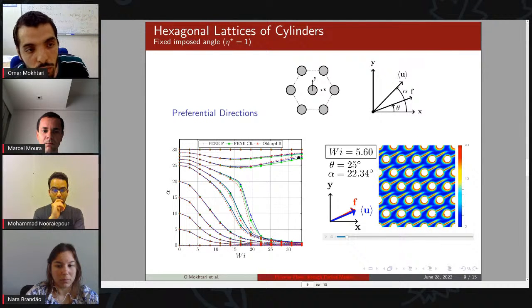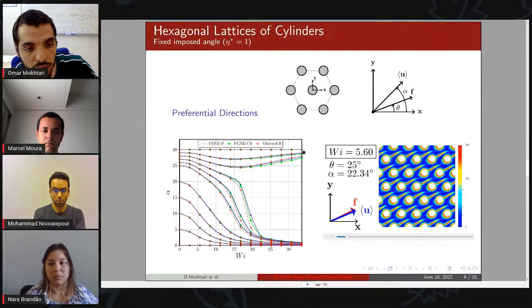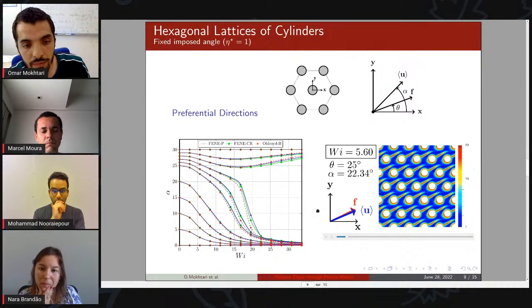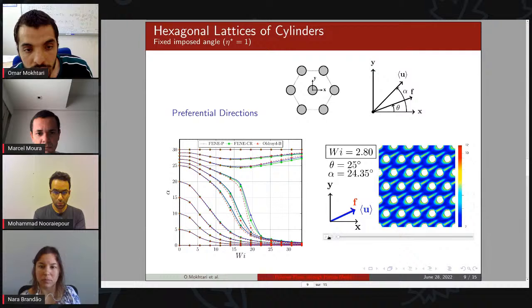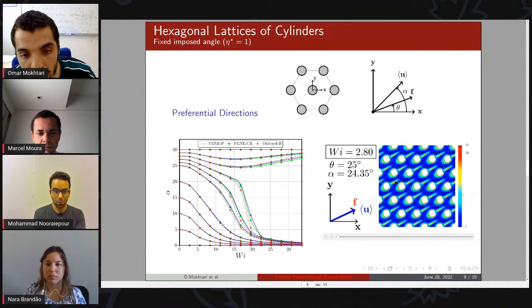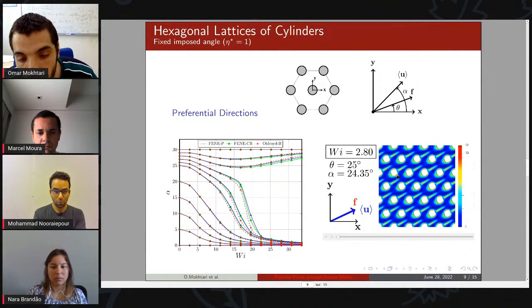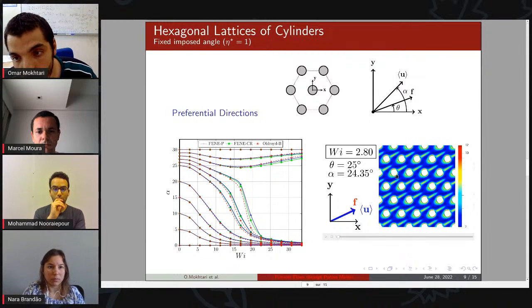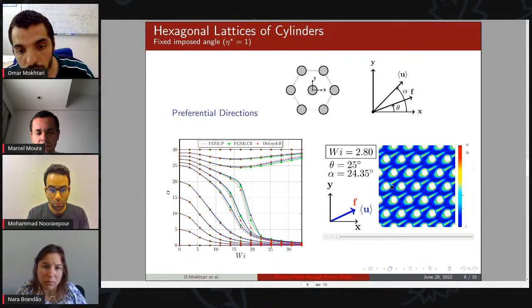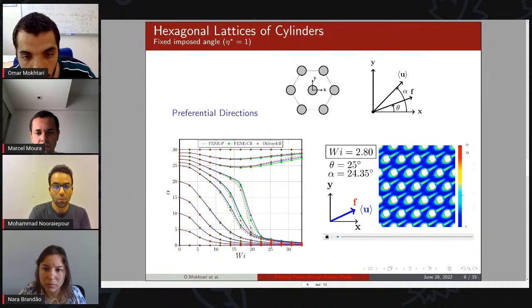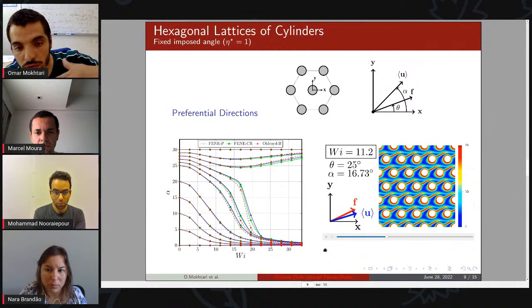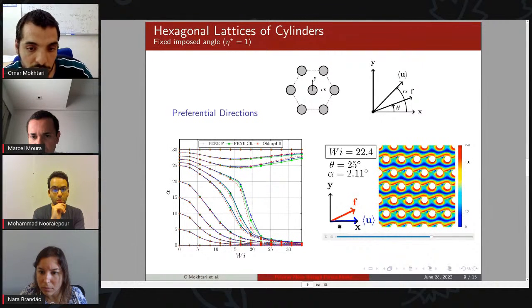So at the end, we have only two preferential directions of the flow, at 0 degrees and 30 degrees, and we can see that 0 degrees is more stable than 30 degrees. To explain what happened, this mechanism can be explained with strands, where in the case of theta equal 25, we have a pre-existing preferential flow on the left of the strands. So by increasing the Weissenberg number, this preferential flow will be enhanced, and the flow on the right will decrease. And we can see that by increasing the Weissenberg number, the strands go to a horizontal position.